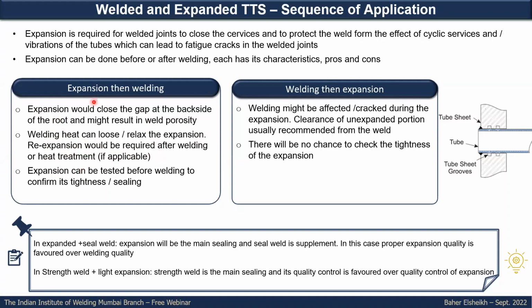And one of the features of expansion then welding is that, by doing the expansion first, you can do some testing, like a leak test or hydro test, to confirm that your expansion is intact. Then you can apply the welding. This is one feature. But if you think of the opposite, welding first, then expansion, during the application of the expansion you might cause some cracking to the weld itself. We will have some examples in the case histories where the weld was applied, then the expansion, and there was some contribution to leaks because of this application.